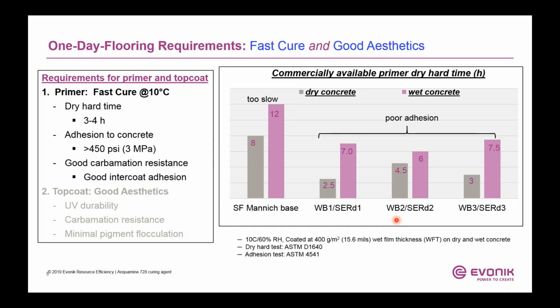When I say wet and dry concrete, concrete is a very porous substrate. Dry concrete is a concrete we don't intentionally expose to water, and wet concrete is a concrete slab that has been soaked in water for a minimum of 24 hours before being taken out for tests. Wet concrete usually contains about 3 to 4% moisture, and dry concrete has 1 to 2% moisture content. So let's look at a solvent-free mannich base system first.